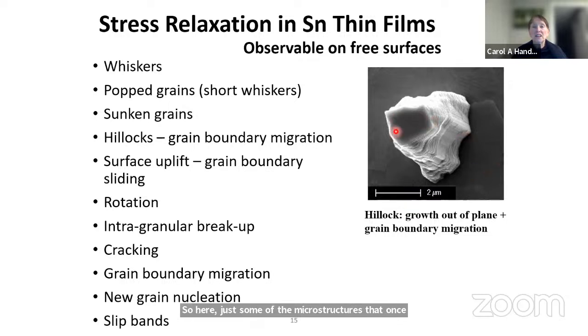This is a hillock. This is the original grain that popped up. Grain boundary migration took place, and this is the final position of the grain boundary. The shallow grain is underneath. So we have a lot of different features of the stress relaxation, many of them just how the individual grains shape. The grains actually rotate. They can break up. Cracking, grain boundary migration, new grains can nucleate, and slip bands. So we're focusing on dynamics and the microstructure.